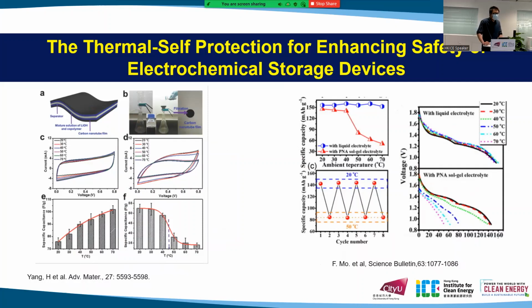So when the temperature increases, the inner resistance increases, so the capacity decays. But when we look at these two works, we find that no matter whether you form a thin film or add the thermosensitive polymer in the electrolyte, the reaction was not fully stopped. You can see there's still some capacitance and specific capacity here, which means that the reaction is there, the water splitting is there, so the issue is still there. So back to our design, how could we do this?